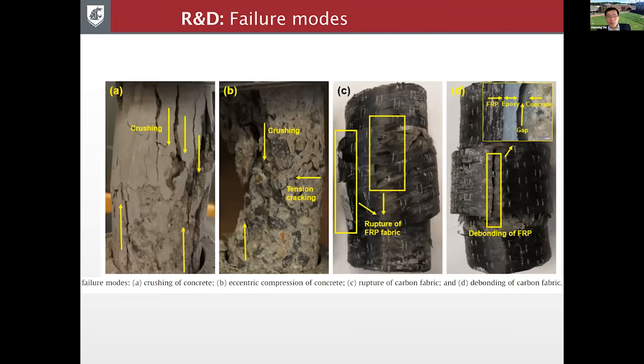So what about failure mode of these small cylinders wrapped in FRP? You can see we observed several different failure modes. One is crushing, relatively homogeneous, which is figure A. Figure B, you are seeing some eccentric compression. So this crushing, and on the other side, you have some tension-induced cracking. And figure C shows a third mode of failure, which is rupture of the FRP fabric. And figure D shows the very last failure mode, which is debonding of the FRP. Usually you see that with the pre-aged concrete, which is much weaker, and after many freeze-thaw cycles, so the concrete was really compromised.